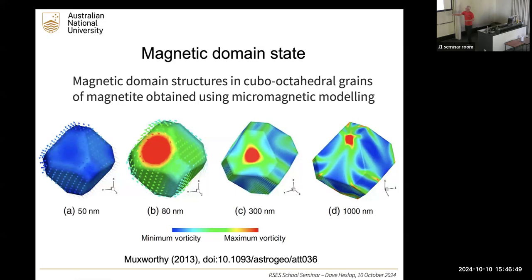Okay. By the time we get to 300 nanometers, the energy minimization has actually split the particle into different zones that we refer to as domains, and the domains will be magnetized in different directions so that they cancel each other out. Okay. Again, this is just a strategy for lowering the energy of the particle. By the time we get to 1,000 nanometers, again, you can see these domains in blue much more clearly. So the only thing we're changing here is particle size, but the moments of these particles as a function of field are dramatically different. Again, somebody saying, I have magnetite particles, doesn't actually tell you very much in terms of magnetic properties.